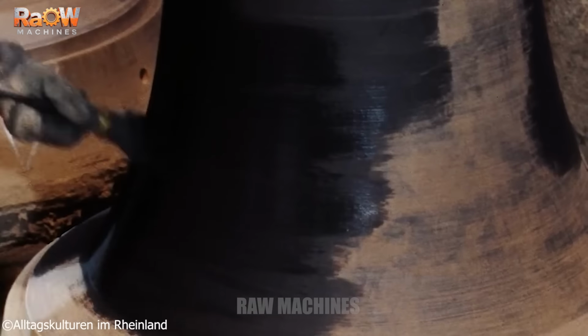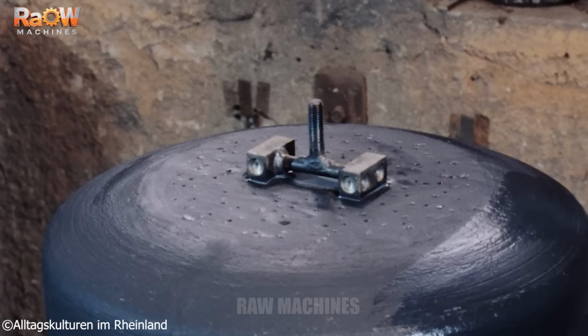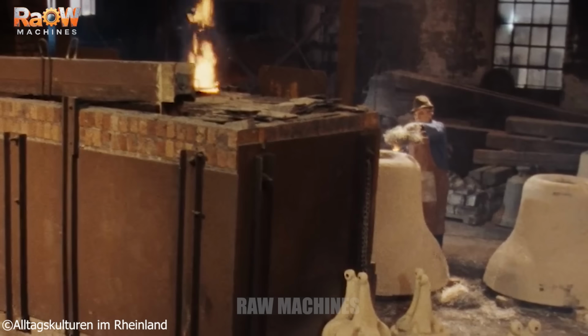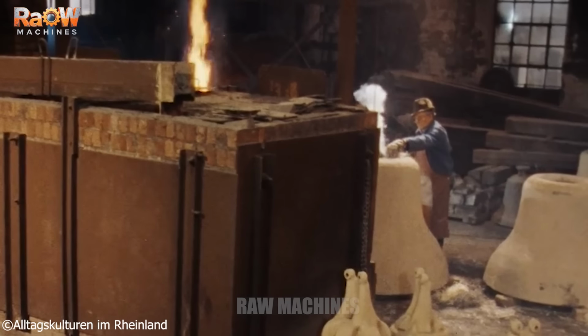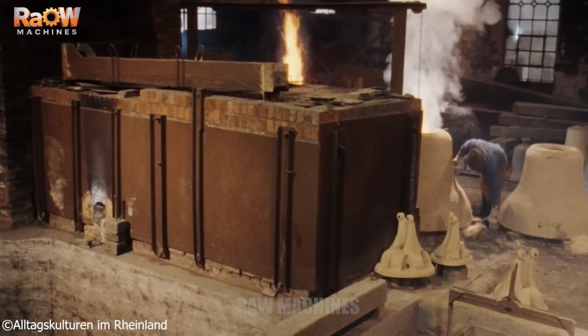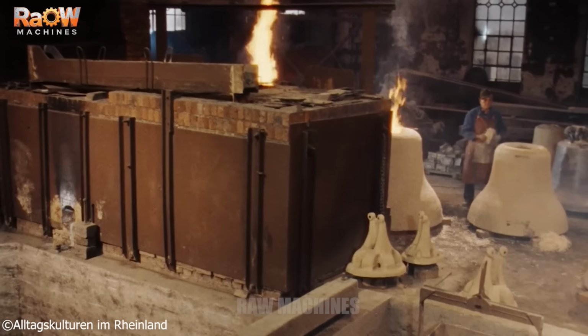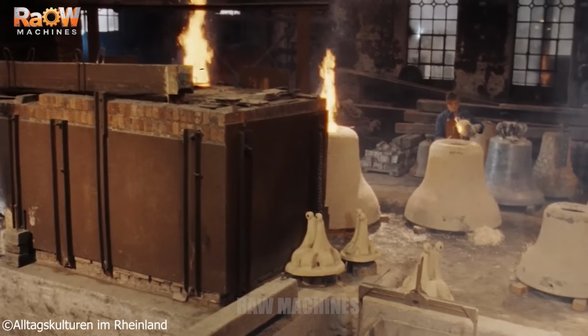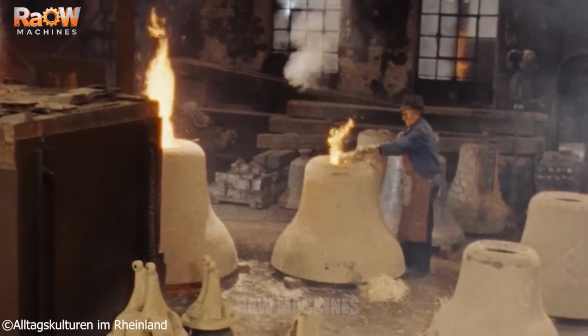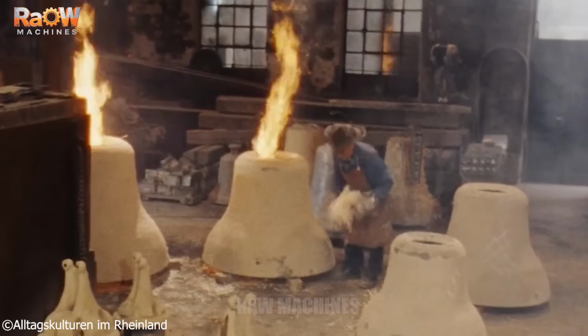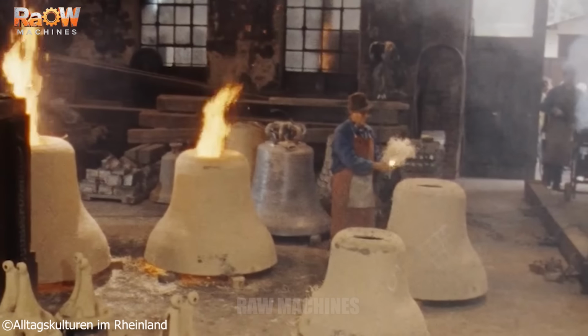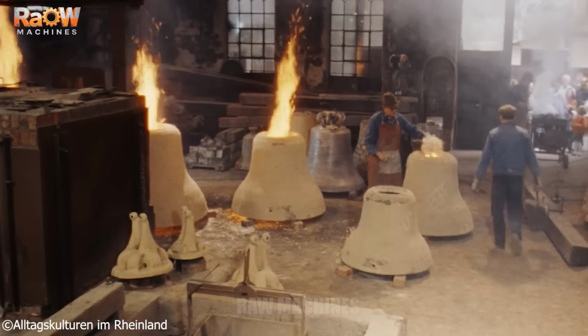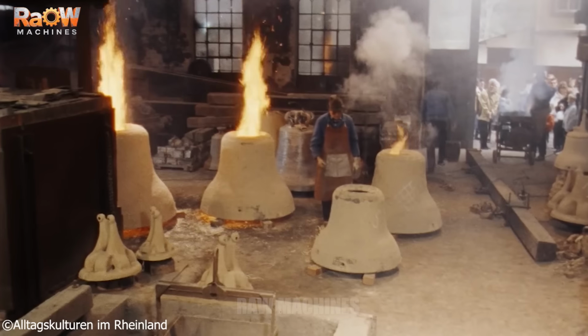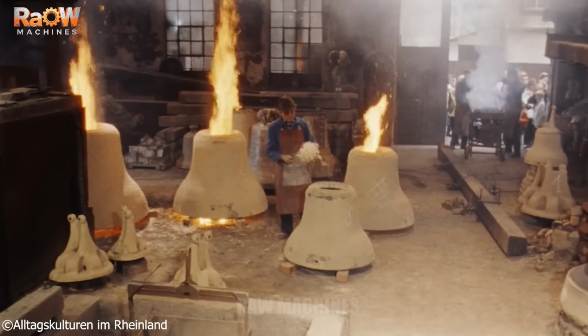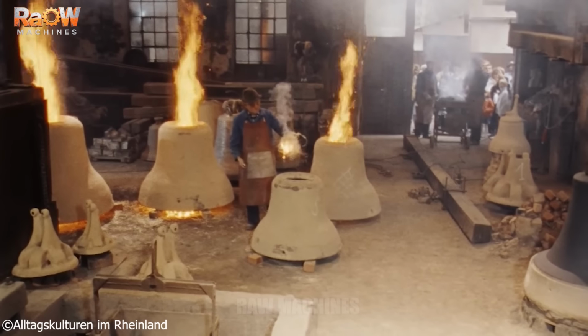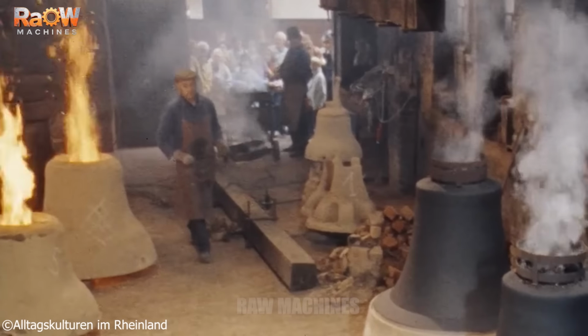At the end of the workday, the molds for the Merzig peal are heated and thoroughly dried. The outer shells are warmed from the outside, while the cores are fired internally to remove any remaining moisture. Before being lowered into the casting pit, each mold must be uniformly dry and warm to prevent cracking caused by thermal shock. In traditional bell casting, even a trace of moisture or an incorrect temperature can destroy a mold, rendering months of preparation useless.